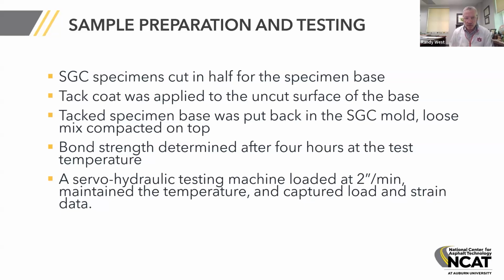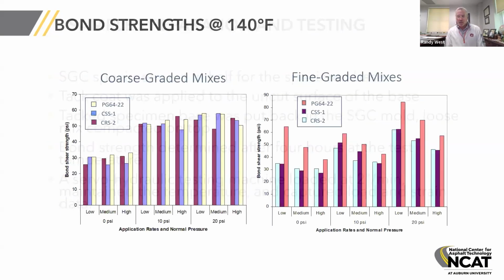And we did it at 3 different temperatures after letting the specimens condition at that temperature for 4 hours. We used a test frame that was a servo hydraulic test machine, but we loaded all the specimens at 2 inches per minute and used the temperature control cabinet to maintain the temperature, and we captured the load and strain data with the loading system. So I'm not going to get into a lot of detail on the results.